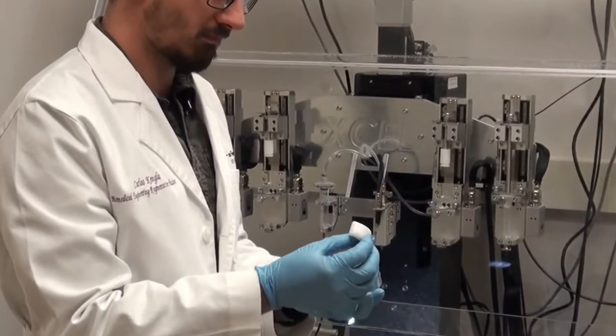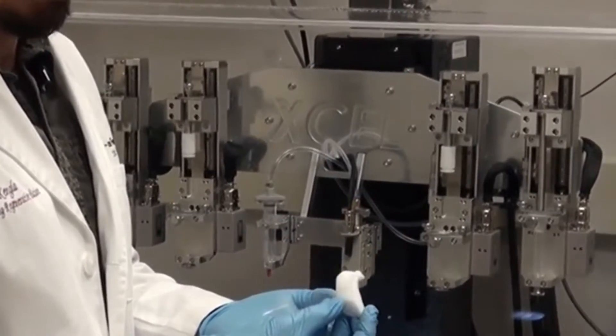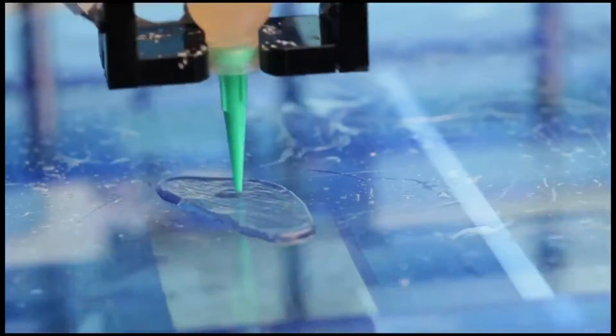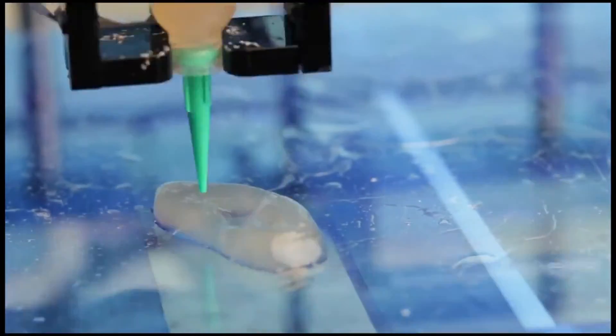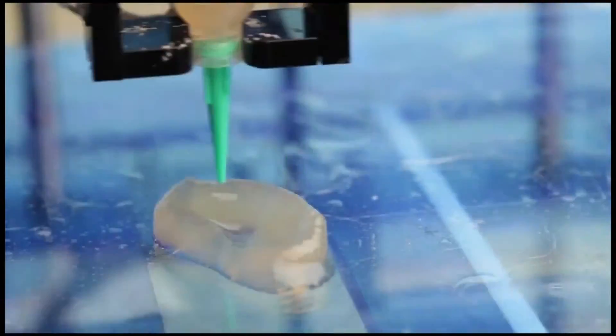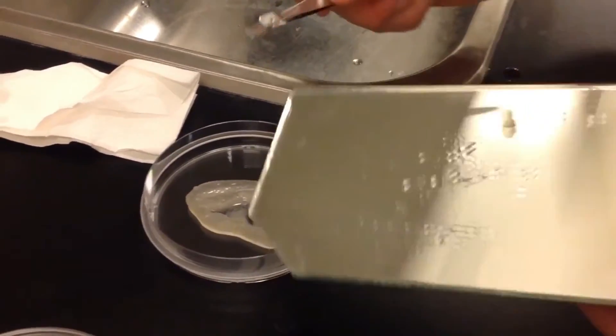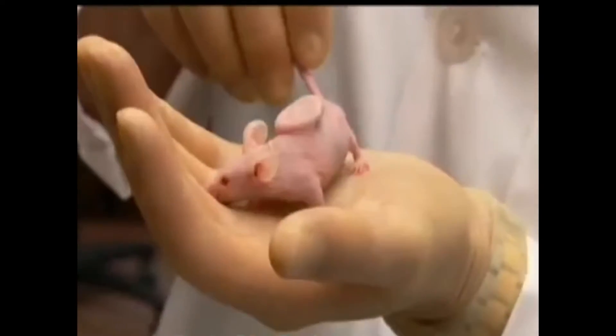The cells in the hydrogel bioink transition to form tissues by secreting their own matrix, which replaces the degrading hydrogel. Many cartridges are used to deliver the hydrogel, and each is connected to a nozzle and an air pressure controller which precisely controls the volume dispensed. The process first starts with a CT scan of an ear, whose information is used to create a topographic 3D computer model. The 3D model is translated into a visualized motion program that guides the bioprinter nozzles to take specific paths for dispensing cells. The next stage involves the bioprinter layering the cells following instructions from the motion program, creating the preliminary ear. When placed in a culture medium for five weeks, the construct produces new cartilage around itself. Researchers have confirmed the maturation of the printed ear constructs in vivo through implantation in mice, reporting good maintenance of shape as well as cartilage formation.